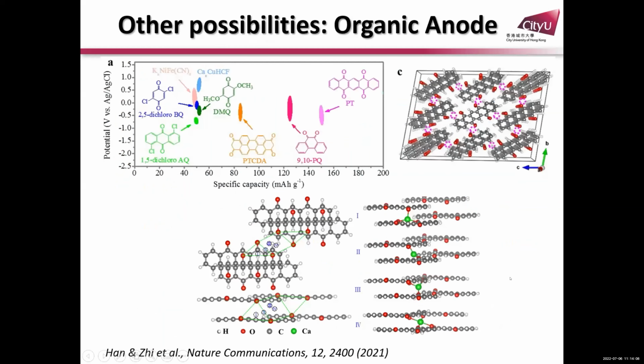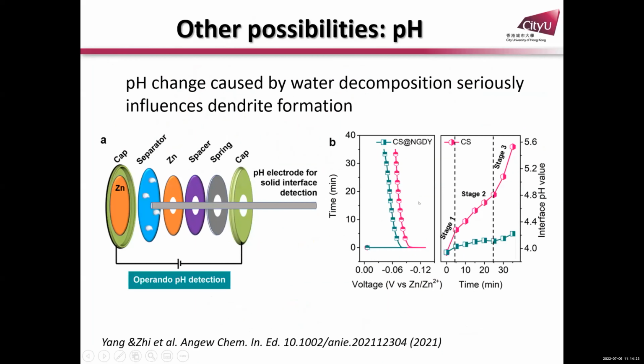Then use this kind of pre-deposited zinc for batteries or full batteries, and you will have much better stability. We're also trying to develop different types of organic anode. Using organic materials can be much better, although it cannot totally solve the problem, because it provides a kind of frame to store zinc, to store different metal ions. And we also study pH value. For example, at the zinc side, you can notice that the pH value increases during cycling. That will affect the dendrite growth.